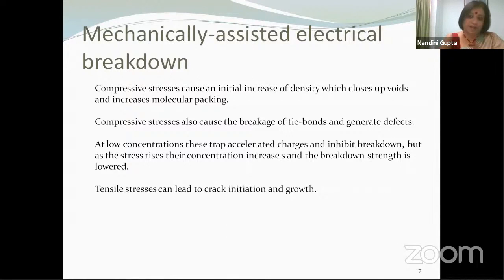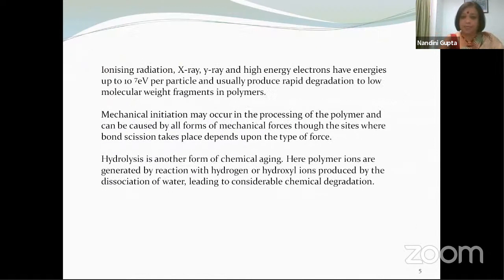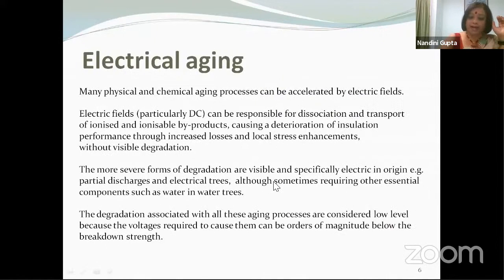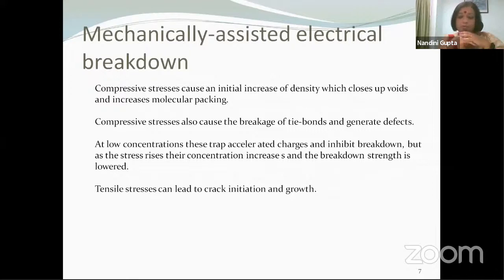Instead of compressive stresses, if you have tensile stresses, it is possible to have crack initiation and growth. If you remember yesterday's lecture, I talked about mechanical stresses due to partial discharges. And I said the kind of energy that you have in partial discharges is unlikely to actually cause crack initiation. But when you have a material aging over a long period of time, and there is a lot of mechanical tensile stress on the material, you can have a considerable amount of mechanical stress accumulated so that cracks can initiate. When cracks initiate and continue to grow under mechanical stresses, we know what will happen. In those cracks, streamers will happen, partial discharges will happen, and the partial discharges will then drive the material to break down over a long period of time.